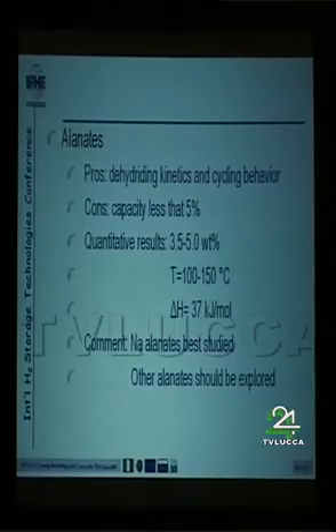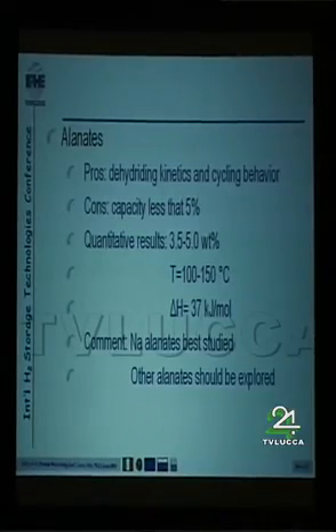Okay. So, alanates. Pros and counters. Pros are dehydriding kinetics and cycling behavior. Promising, positive. Counters are capacity less than 5%. The quantitative results obtained up to now are for storage capacity from 3.5 to 5 weight percent at temperatures between 100 and 150 degrees centigrade with enthalpies of about 37 kilojoule per mole. The comment is sodium alanates are best and most studied. Other alanates should be explored.